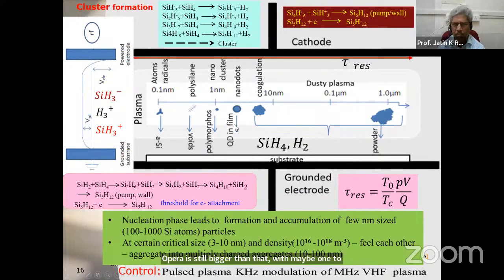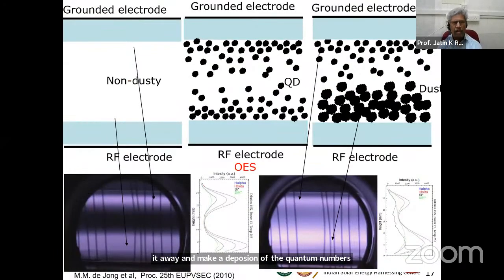they're called nanodots or quantum dots, and they can go to the substrate and deposit. If you go bigger than that, they will coagulate and finally become dusty plasma. And this is not what you want. Normally it should be removed. So the whole idea is that before it goes there, you have to pull it away and make a deposition of the quantum dots.